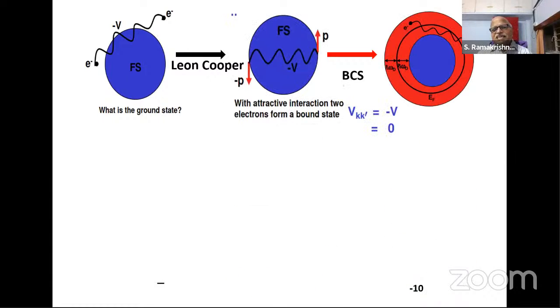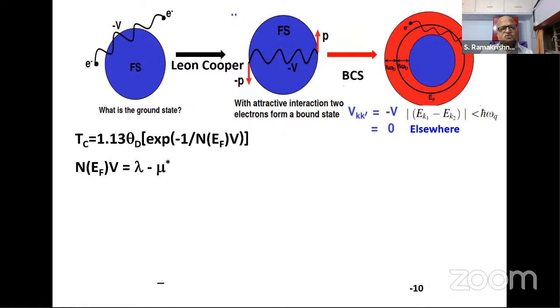Then Bardeen and Schrieffer took this idea and showed that if you look at a thin window of energy scale close to the Fermi level, which I have very much exaggerated, where ħω is tiny compared to E_k and E_k', then in a tiny shell we can have an attractive interaction and it is zero otherwise. If you assume such a small window is responsible for superconductivity, you can find an expression: the superconducting T_C is related to the Debye temperature, the density of states at the Fermi level, and the interaction between the two electrons just outside, close to the Fermi surface.